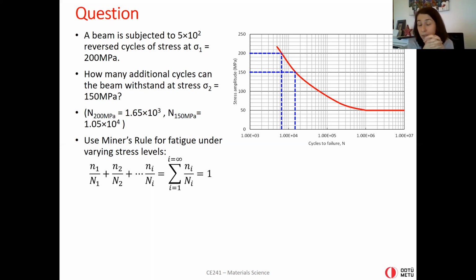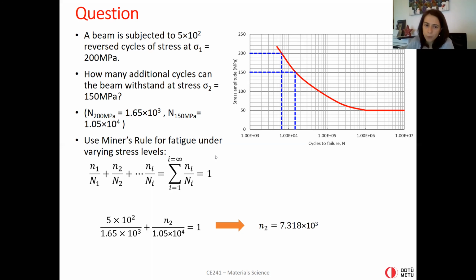number of stress cycles you have gone through in the first stress divided by its lifetime, plus number of cycles that you have gone through in the second stress divided by lifetime in the second stress. These should add to 1. So 5 times 10 to the 2 divided by 1.65 times 10 to the 3. This is the 200 megapascal portion, plus number of cycles under 150 divided by lifetime under 150 megapascal, which is 1.05 times 10 to the 4. This should add up to 1. So you can solve for it, which will give you 7,318 cycles.